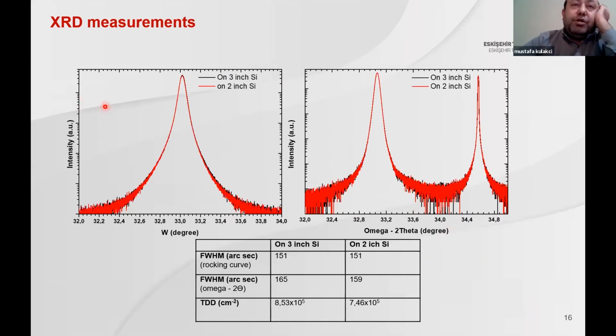Okay, when you look at the measurements, both the rocking curve at the left-hand side and the omega-2 theta scan at the right-hand side, you see the gallium arsenide 004 plane and silicon here as a 004 plane. And the best achieved result structurally, in full width at half maximum, is about 150 arc seconds. And also when you calculate the TD dislocation density, it is lower than 10 to the 6 per centimeter square. Actually, in this calculation, of course, we also include the buffer layer, which means that our active solar structure defect density, threading dislocation density, should be much lower than this.